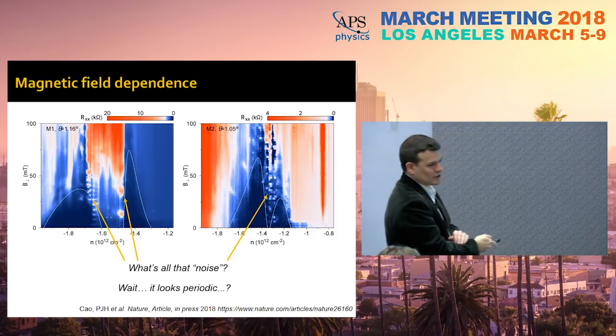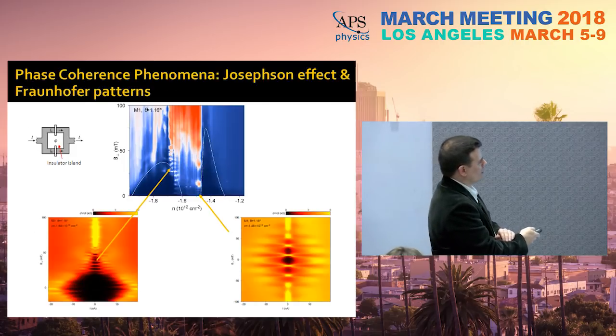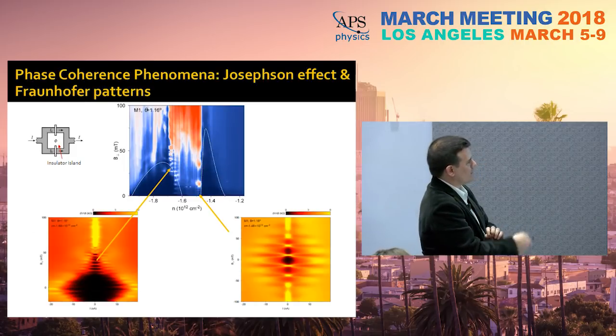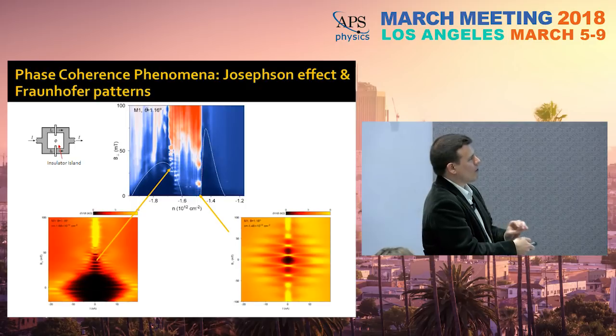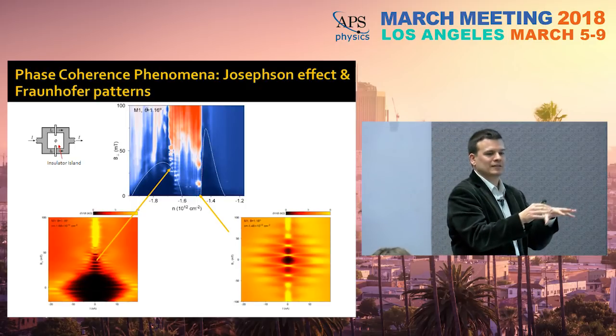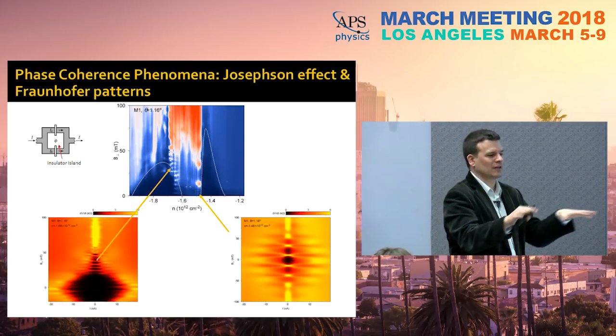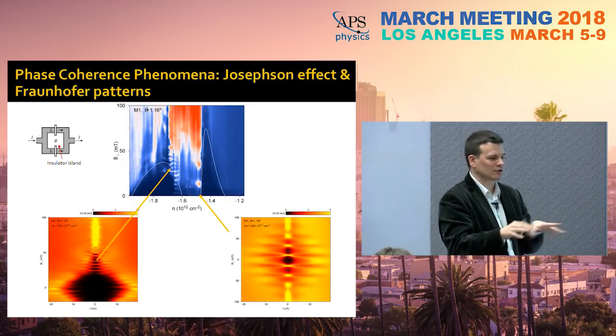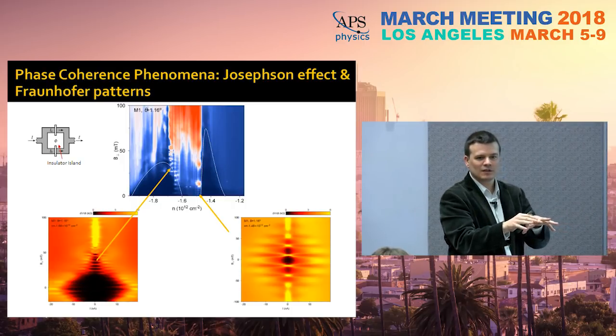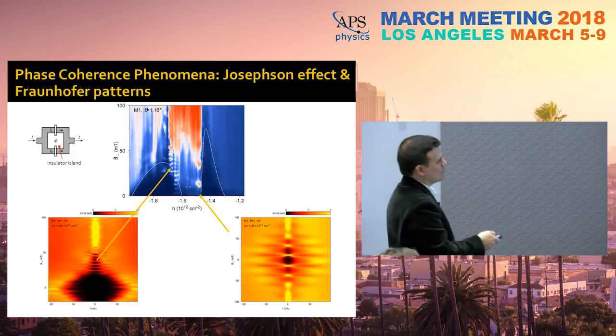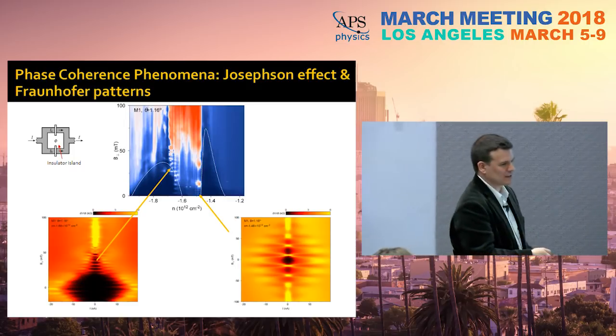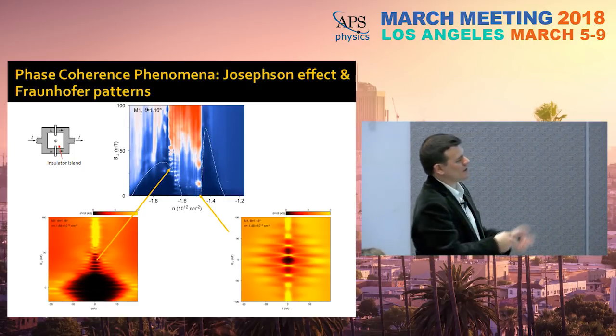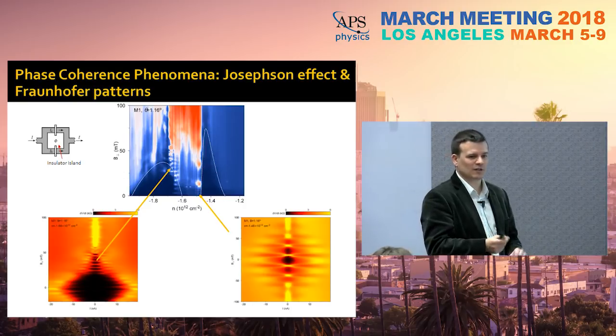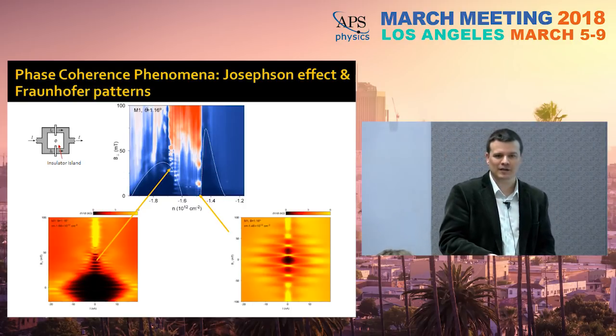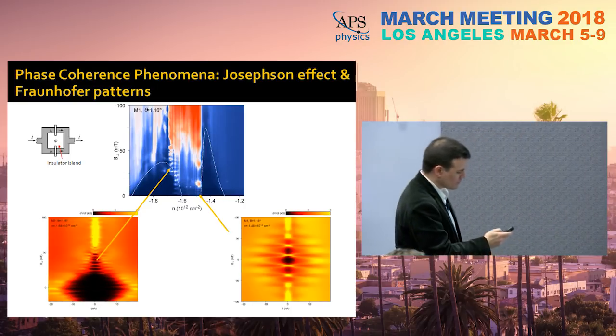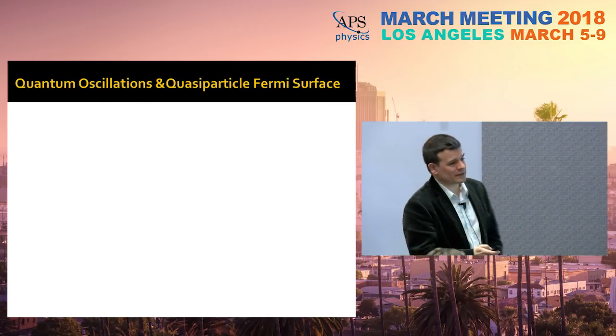So if you actually measure the differential resistance as a function of current bias and magnetic field, you have all these Fraunhofer-like patterns coming from arrays of Josephson junctions, where typically 1 or 2 junctions dominate, okay? So you have this phase coherence phenomenon, which can be modeled. You can look again for details at the paper, mostly with SQUIDs, either symmetric or asymmetric SQUIDs. So typically 1 or 2 junctions dominate this behavior. But the thing gets even better, okay?